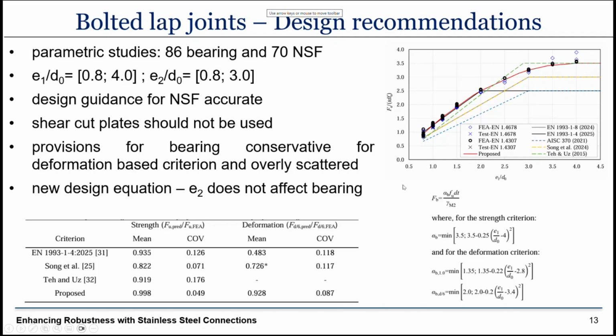Now, for people familiar with carbon steel design, the previous version of Eurocode 3 Part 1-8, the one dealing with design of connections, included dependency on both the end and the edge distance. The recently revised version removed the dependence on the edge distance, so there is no E2 dependence. For stainless steel, though, the newly revised version still retains the E2 dependence, and according to our research, we don't see a reason why that should be happening. So we're proposing that this should be removed.